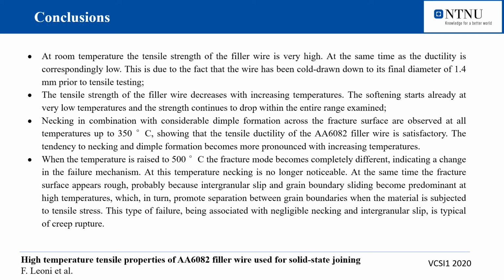Necking, in combination with considerable dimple formation across the fracture surface, is observed at all temperatures up to 350 degrees Celsius. This shows that the tensile ductility of the aluminum alloy 6082 filler wire is satisfactory. The tendency to necking and dimple formation becomes more pronounced with increasing temperature. But when the temperature is raised to 500 degrees, the fracture mode becomes completely different and indicates a change in the failure mechanism. No necking is visible and the fracture surface appears rough. This type of failure, as said before, is typical of creep rupture.